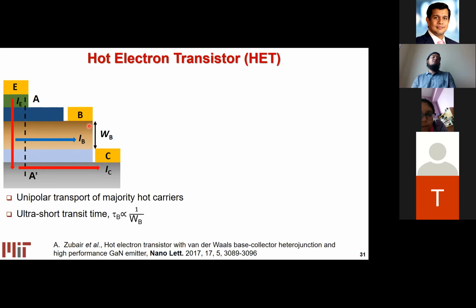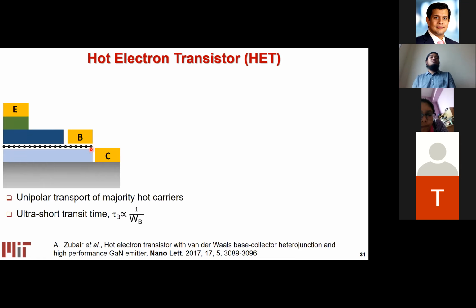To increase the frequency, one idea was, why don't we just thin down this base thickness, and that should give us the highest possible frequency, because the base thickness limits the transit time of the carrier. So people have tried over the years many different materials, including gallium nitride. What we proposed a few years ago is basically, why don't we use a single atomic layer base between these insulating layers? It has to be a single atomic layer, and graphene can be an attractive option.